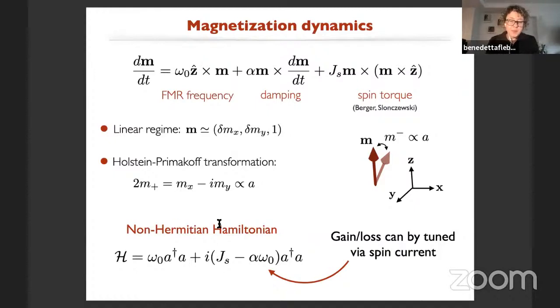This Hamiltonian is the linearized version of this type of dynamics. Here we find the usual Hermitian term, which tells us the FMR frequency of these modes. And here we find the non-Hermitian terms, in which it becomes obvious that the spin current, if polarized in the proper direction, acts against the damping. From a physical point of view, I think it's quite simple to imagine: our order parameter is damped, and then we pump spin current in, so we pump extra spin angular momentum, therefore more magnons in the system, and this will counteract the magnetic dissipation. So that's how this term is acting.